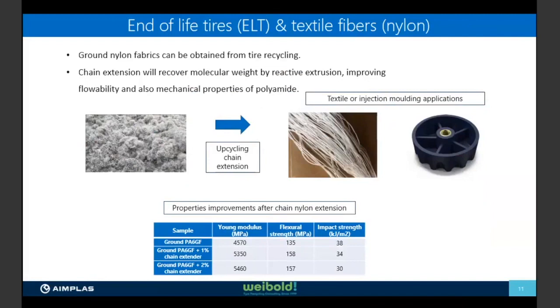Here and down, you can see in this table one example that we made with the ground polyamide with glass fiber. You can see in the first row the properties of the ground, recycled polyamide with glass fiber. And as we add a chain extender, you can see the improvement in the mechanical properties, in the Young's modulus, in the flexural strength, and also keeping improving properties related with stiffness. At the same time, keeping impact strength, which is related with toughness, at very decent values. So chain extenders are not so much used in the world of plastics, they are quite unknown additives, but are very effective when we try to recover properties in polymers like polyamide, and this could be one example.